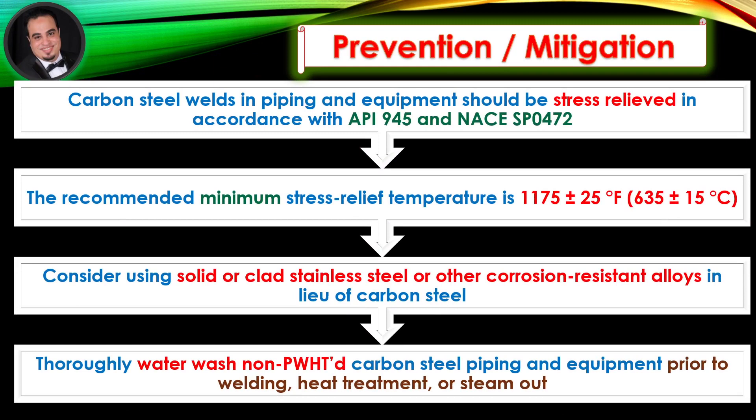Mitigation: carbon steel welds in piping and equipment should be stress relieved in accordance with API 945 and NACE SP 0472. The recommended minimum stress relief temperature is 1175 ± 25 degrees Fahrenheit. Consider using solid or clad stainless steel or other corrosion resistant alloys in lieu of carbon steel. Thoroughly water wash non-post-weld heat-treated carbon steel piping and equipment prior to welding, heat treatment, or steam-out.